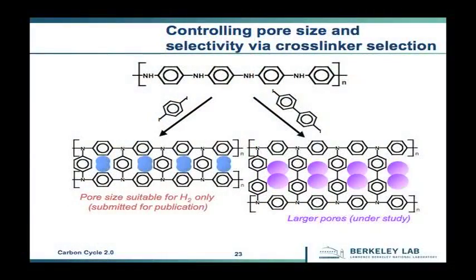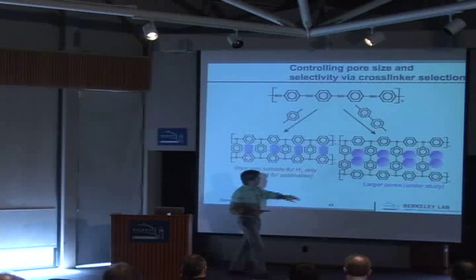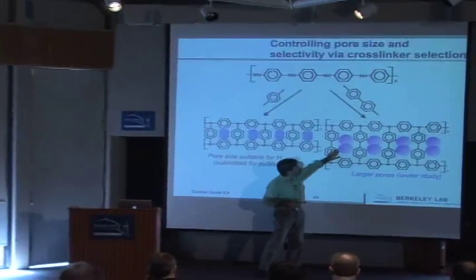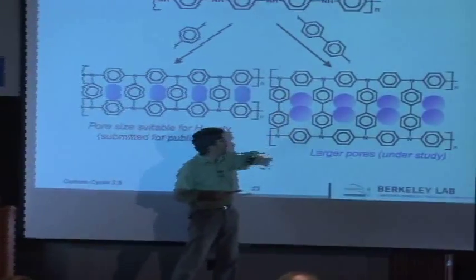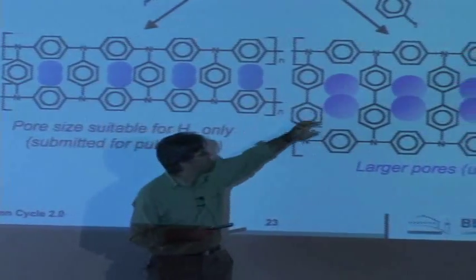So the type of materials they're looking at are those hypercross-linked materials where you actually introduce pores by changing the length of these crosslinkers. So if you have short ones, you get small holes and you get something which is only permeable for hydrogen. But if you make them larger, you actually get pores which you may be able to use for the separation of CO2. And what you can do on top of that is introduce some chemical functionality, for example, introduce amine groups at the various benzene components to further increase the selectivity.